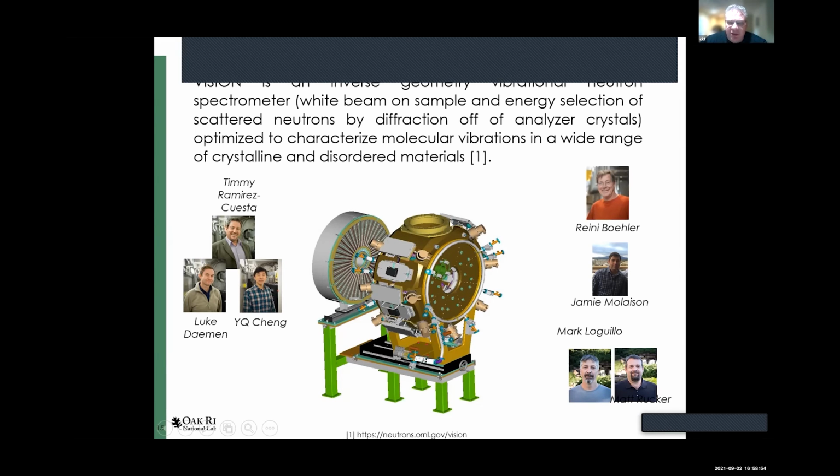But if you look at the instrument, at the top here, if you can see my cursor, this is where the sample goes. So the sample actually goes down in a hole and is suspended from a flange. And there's virtually no positioning capability of the sample. You have to realize that most times in neutron scattering, samples are cubic centimeters, and beams measure centimeters in dimension. So this illustrates the challenge of doing a diamond anvil cell experiment when the diamond cell is suspended from a flange and basically put down in a manhole.